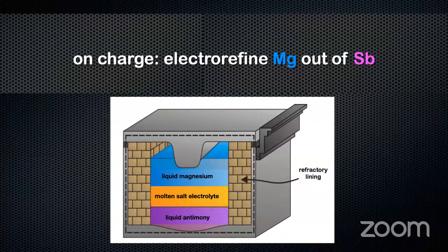And by the way, when the battery is discharging and the current is flowing, it generates heat, which is the threat to the lithium-ion battery. We take that heat and trap it and use it to keep the battery at temperature. So the battery discharges for, say, 4 or 5 hours. We trap that heat, and then it sits idle. Then we charge the battery 4 or 5 hours, generate heat, trap it, and it sits idle. And by the normal use of the battery on a daily basis, it generates the heat to keep itself at temperature. We have to put some energy in to get the thing started, and after that, by cycling, and it wants to be cycled. This is not a battery that just sits there waiting in case there's a hurricane or something. No, we want this running all the time.